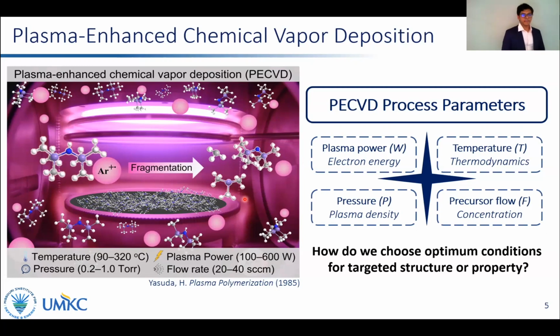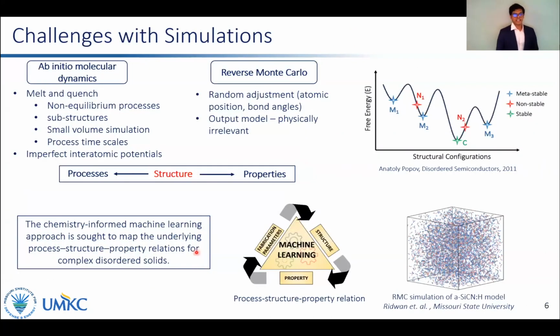It would have been easier if we had the ability to simulate these fabrication processes, but unfortunately, we cannot reliably do so with existing computational methods. Conventional molecular dynamics simulations use a melt and quench strategy, which involves packing a simulation box with molecules, increasing its temperature, and then cooling it down to an amorphous state. Unfortunately, these simulations do not consider the non-equilibrium processes that are actually happening in fabrication, and cannot retain the substructures associated with multiple potential minima on a vast potential energy surface diagram.